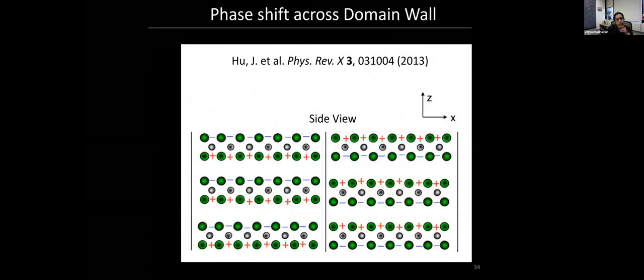So as it turns out, this FeSeTe is really intriguing because Jianping Hu wrote a paper in 2013 where he showed that if you consider all the important interactions, nearest neighbor, next nearest neighbor, and so on, then what you find is a very interesting kind of superconductor where, so this is one of the layers. This could be Fe arsenic arsenic, or iron selenium selenium.